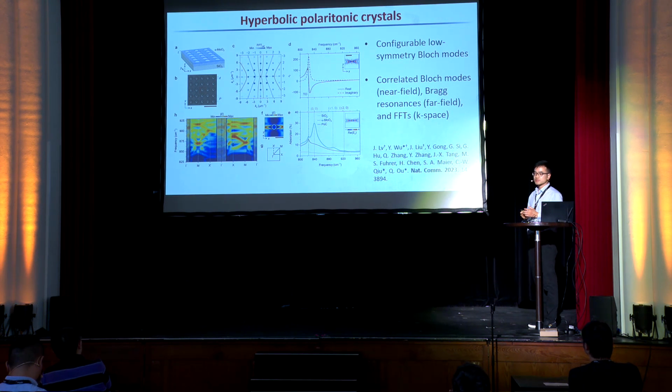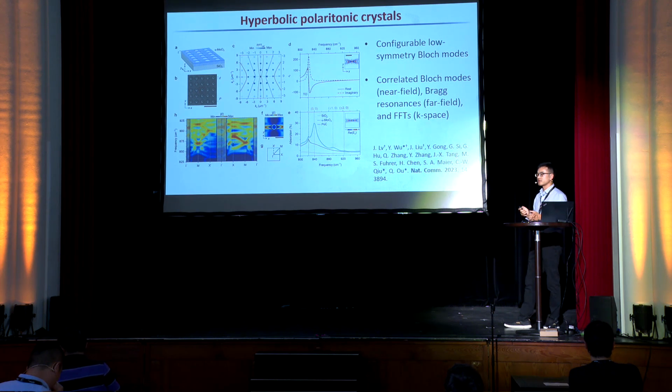So that's the main point of these photonic structures integrated into in-plane hyperbolic materials: you need to consider such momentum matching between the nanostructure vectors and the hyperbolic dispersion. There should be some momentum matching, then it will excite the phonon polaritons or photonic modes.